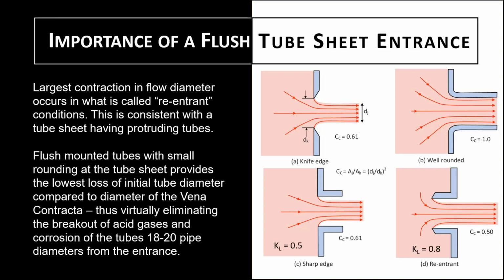Entrance designs can not only reduce the head loss via reduction in the KL value, but they can also reduce the difference in cross-sectional area between the entrance and the vena contracta. If we look at the bottom right picture, which is called a re-entrant condition, which is consistent with a tube sheet that has protruding tubes coming out of the tube sheet, you can see that it has the smallest area factor, which means the velocity of flow will be the highest, and it also has the highest KL compared to the other flow conditions, specifically looking at the bottom left, which is a sharp-edged or flush mount tube inside a tube sheet.